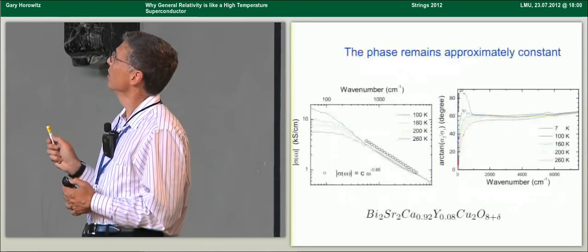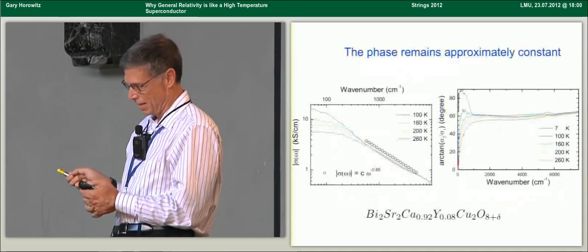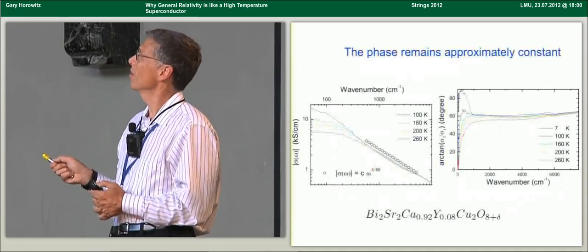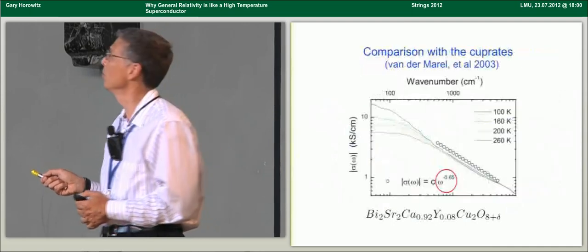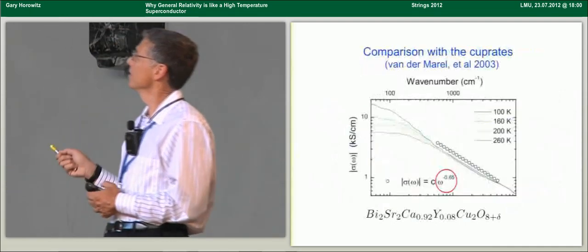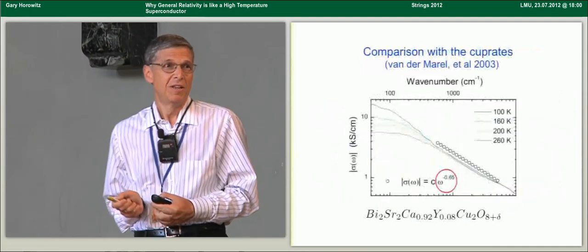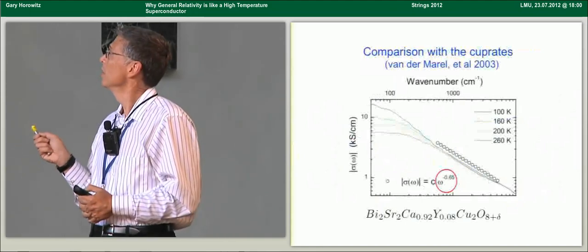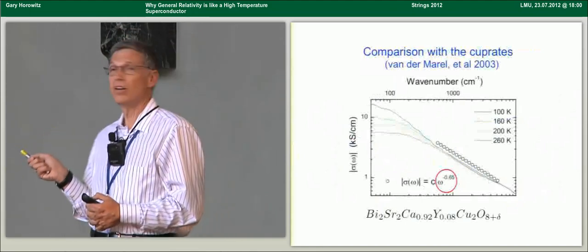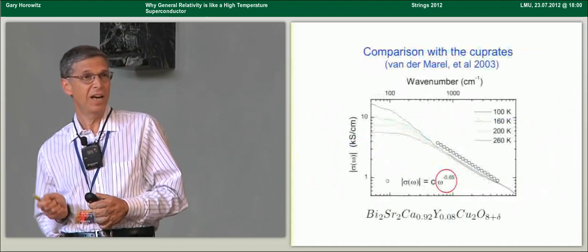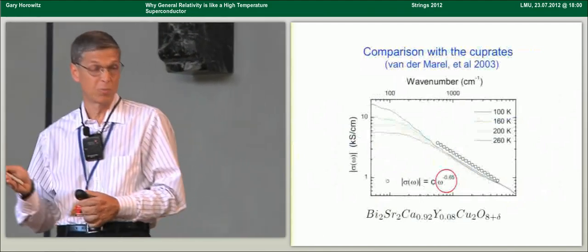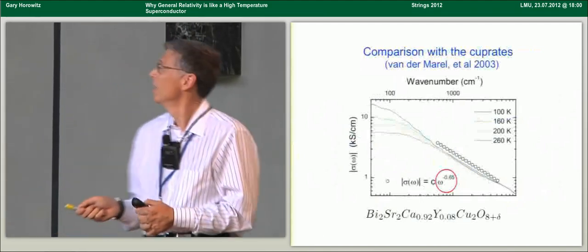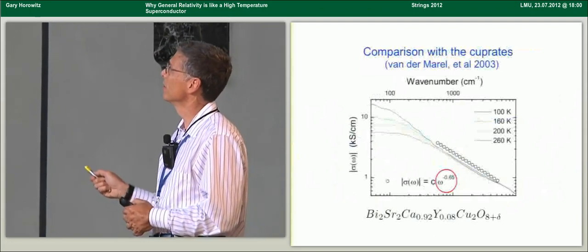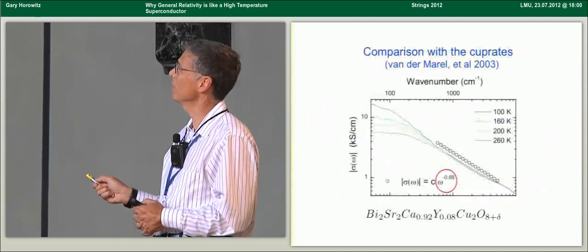I should say, though, going back to here, that there are, of course, some differences between what we calculate and what is measured. First of all, there's no analog of the offset. We had b over omega to the 2/3 plus a constant c. They get a pure power law. Okay, so they don't see any sign of this offset.